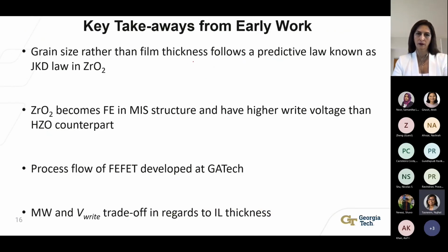So these are some key takeaways from my early PhD work, which indicates that grain size follows a predictive law known as the JKD law in zirconium oxide films. We also saw that zirconium oxide becomes ferroelectric in MIS structure and has a higher write voltage than its HZO counterpart, which is why later on we shifted our attention to HZO.